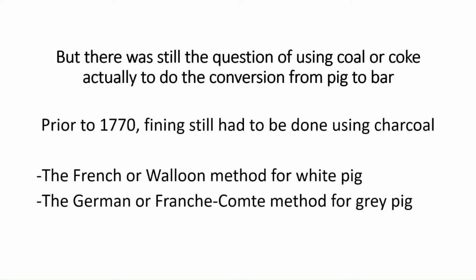There was this question of being able to use coal or coke, actually. The processes had to change when coke iron came onto the market as opposed to charcoal iron, pig iron, because of the silicon content that you had in the iron that came from a coke-fired blast furnace. When they had iron from charcoal-fired blast furnace, they could get away with what was called the French or the Walloon method for fining the pig. But if they had grey iron with a high silicon content, they had to use what was known as the German process or the French Comte process. And the thing about that was that in the latter case, you had to use iron oxide additions to help remove the carbon.